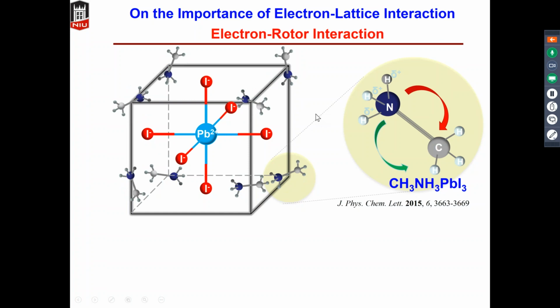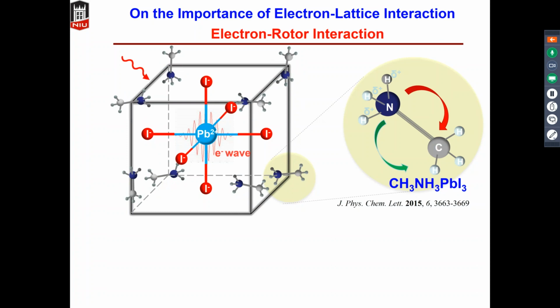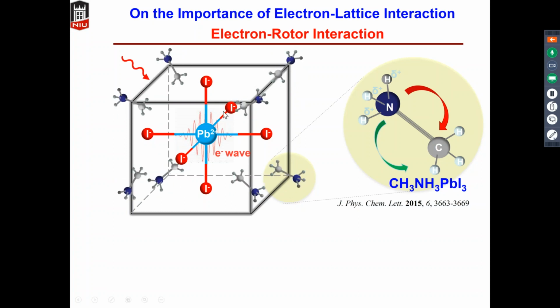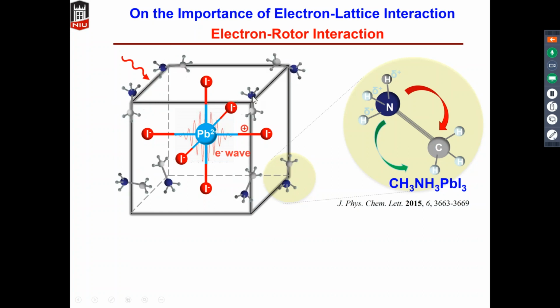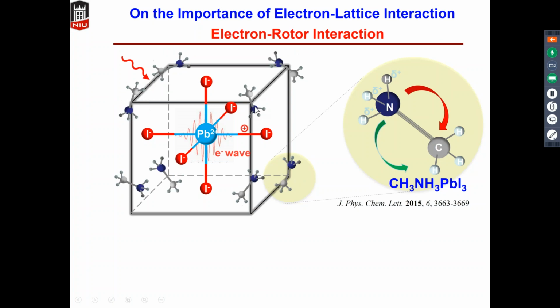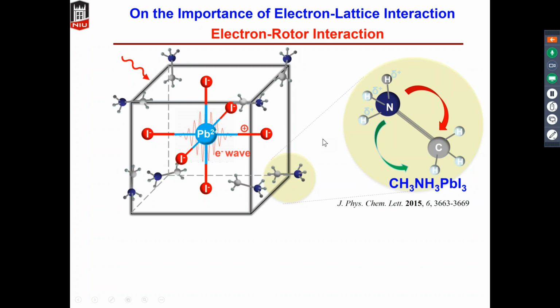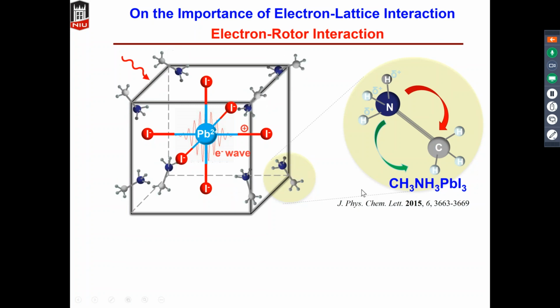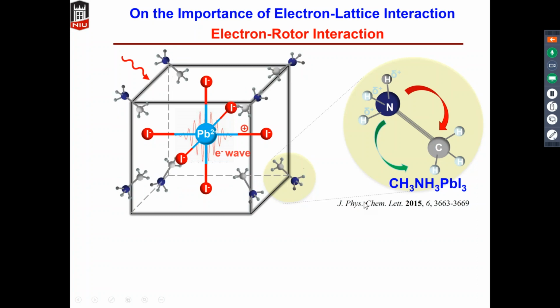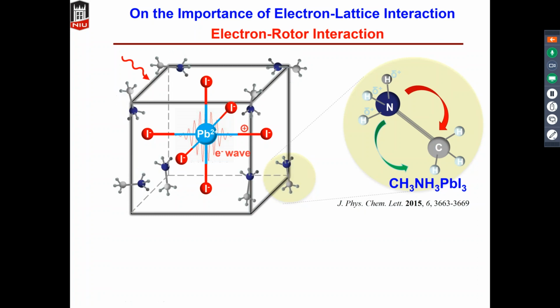And if there's a photo-induced charge generated, then this charge will be subject to the local electric field change generated by the rotation of these, we call them rotors. So there is a certain kind of electron-rotor interaction here. And in order to study this effect, we actually borrowed the idea from physics in the field of superconductivity.